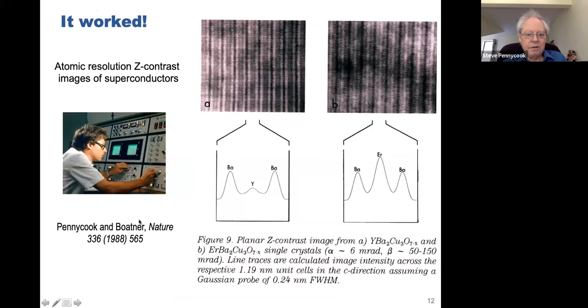And that was when Lynn Boatner was actually making these high Tc superconductors. And you could see the contrast in the image from YBCO with yttrium on this plane. It matches pretty well the simulations. And you replace that yttrium with erbium, the center line goes bright. So it seemed to work.